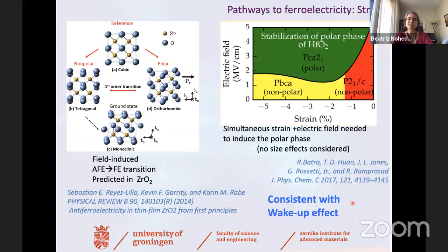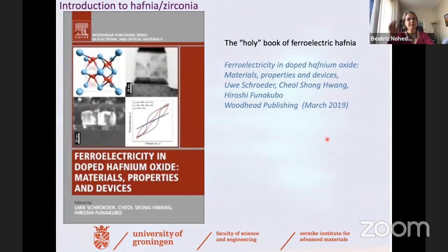This actually is consistent with something that people have seen in these materials, which is what we call a wake-up effect. You make a material, your material is not ferroelectric originally, but it becomes ferroelectric after a lot of cycles, and this is what was called the wake-up effect. And this seems to be pointing in this direction. You may need to apply some electric field cycling in order to create this ferroelectric phase. As I said, many of these effects are very tricky, very subtle, and it took a very long time to understand how exactly doping and strain and electric field and size affect the material. And I recommend you look at this book where everything is explained. It's the holy book of ferroelectric hafnia here.